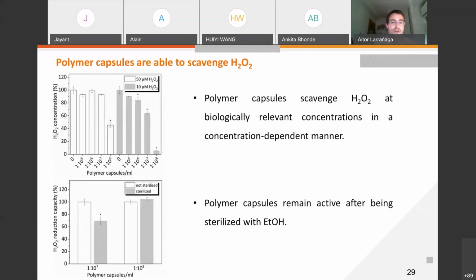After this initial physicochemical and morphological characterization of our capsules, we wanted to prove their antioxidant capacity. We wanted to prove that they were still able to reduce hydrogen peroxide from the solution. And we found at biologically relevant concentration of hydrogen peroxide that these capsules were able to scavenge hydrogen peroxide in a concentration-dependent manner. But more importantly for us in this project was to prove the robustness of our polymer capsules.